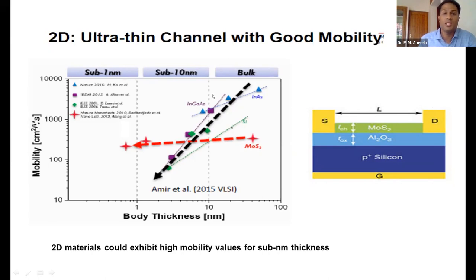But the major problem is that when you decrease the size of this active layer, the mobility actually decreases. If the carriers have no mobility, the electron cannot move to the other end. That is a major drawback when you use other types of semiconductors, like indium gallium arsenide and indium arsenide, etc. The mobility decreases when you decrease the size of the active layer. But in MoS2, you can see that the mobility is almost constant. That is the advantage of this type of two-dimensional material, MoS2. So you can fabricate the transistor with MoS2 as well.